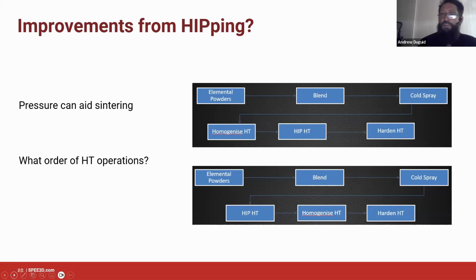So we have a choice: we could cold spray things, homogenize them as we have just seen ourselves do, and then run them through the HIP. Or we could HIP the material first and then conduct all of the heat treatments after the HIPping process, once we've resolved all the defects. It was a hard call, so we decided that we'd check both of those, and it turned out that it was well that we did so.